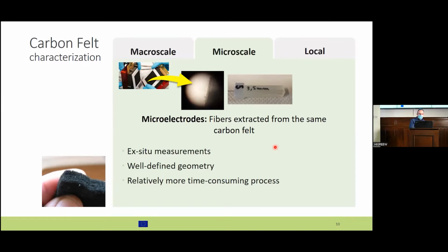This is reported already in the literature. We have the graphite felt, which is made of fibers, and we can extract one fiber. We don't do it once, we do it several times in order to get a little bit of statistics on the analysis. And here we have the fiber, and we simplify the electrode.